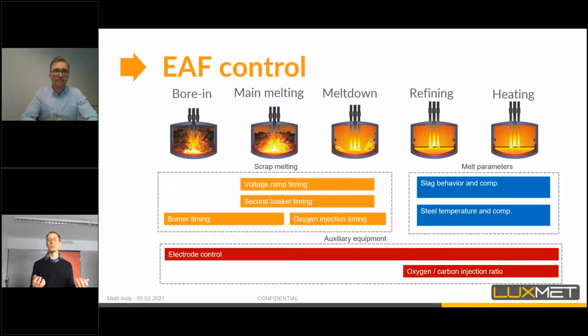And then at some point, the scrap on the sides will melt down, and the sides and the roof parts will start to be uncovered. This has serious consequences for many different electric arc furnace equipment. For example, one thing is the electric arc furnace arc power. When the sides are getting uncovered, we need to either lower the arc length and power or start the slag foaming to shroud the arc in the foaming slag to prevent refractory wear and loss of energy.